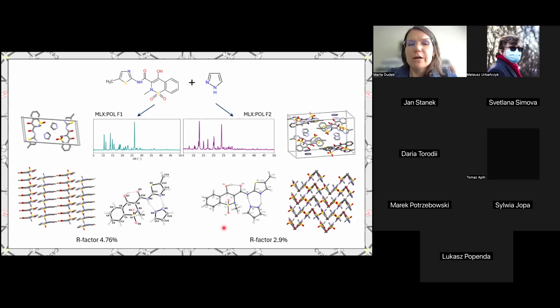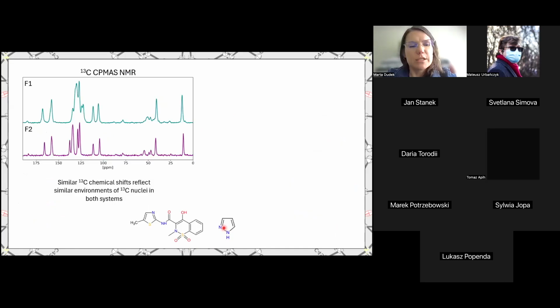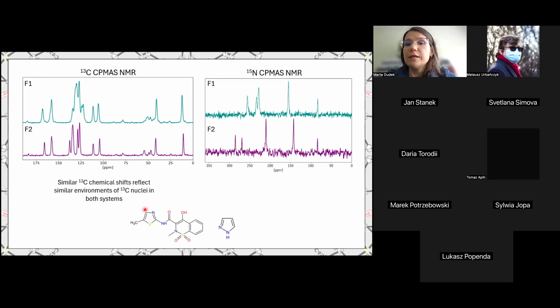one might say, too thorough with our experimental approach and decided to register solid-state NMR spectra. At first, we planned only to register simple CPMAS experiments, so one-dimensional experiments for carbon and nitrogen atoms. And indeed, for carbon-13 NMR, we saw what we kind of expected, because those crystal structures are quite similar. So we expected similar chemical shifts of carbon-13, which reflects similar environment in a crystal. But when we run nitrogen-15 CPMAS experiments, we saw something which could not be explained by the crystal structures that were determined through diffraction methods.